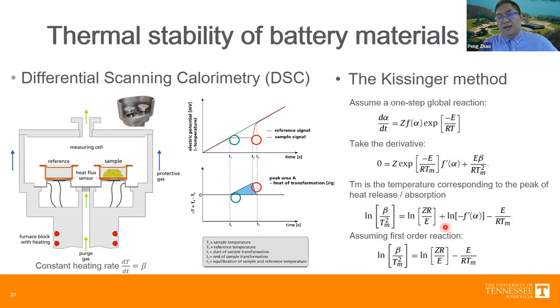And in the case where you have a unity reaction order, this long term is gone. And eventually you can have a very simple formula which is the Kissinger result. Basically, if you can measure the temperature corresponding to the peak of heat release or absorption at different heating rates of the experiment, you can extrapolate the activation energy, you can extrapolate the frequency factor. This method is very useful for simple materials with a single peak or with separated peaks.